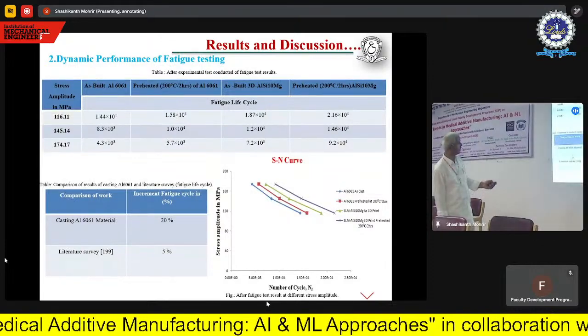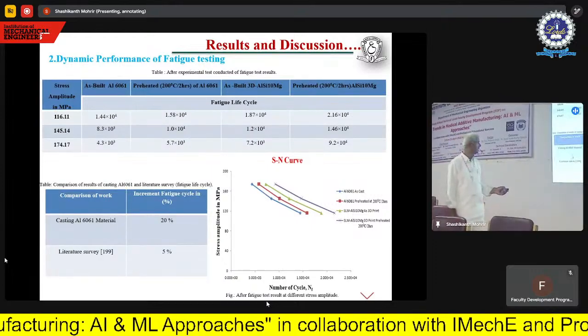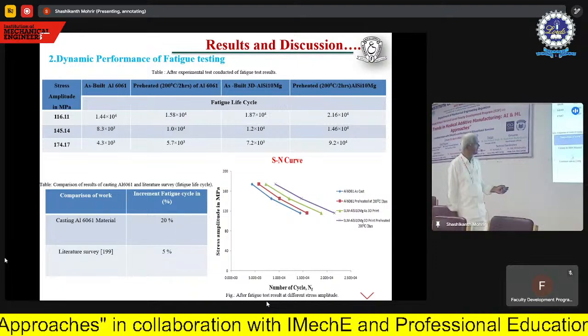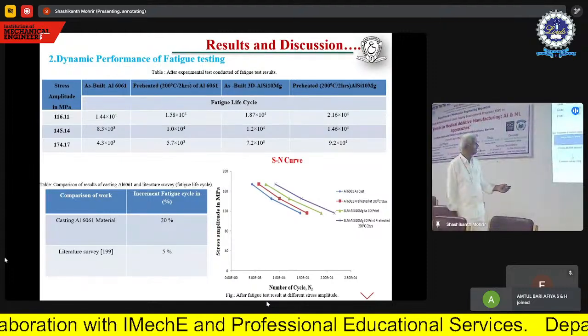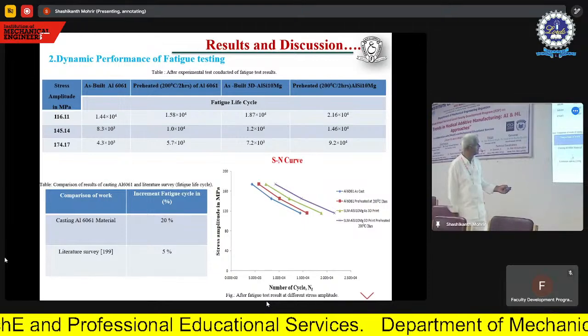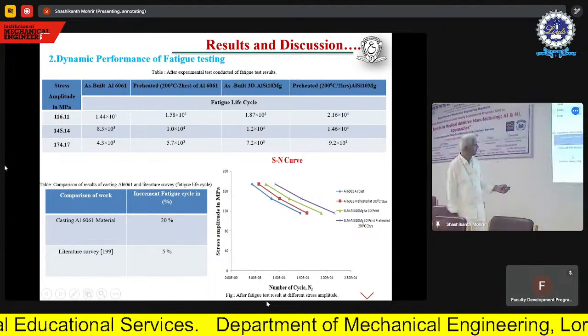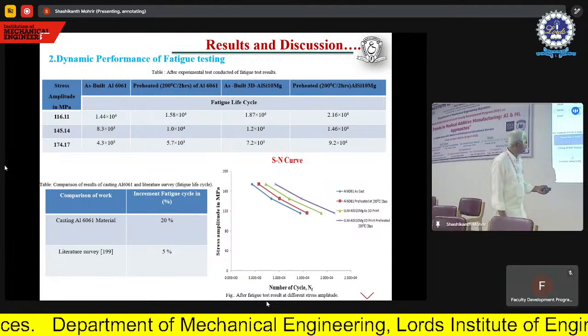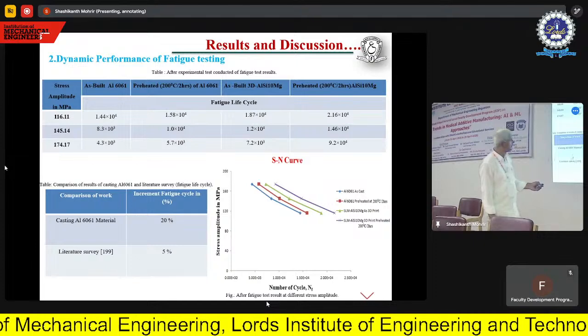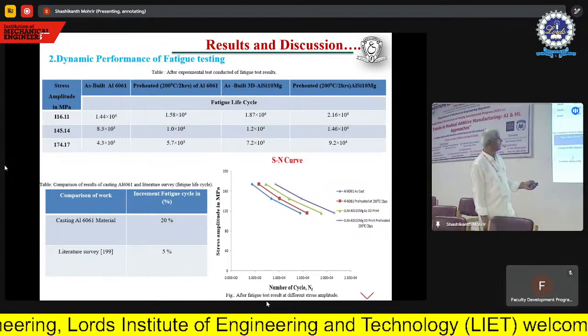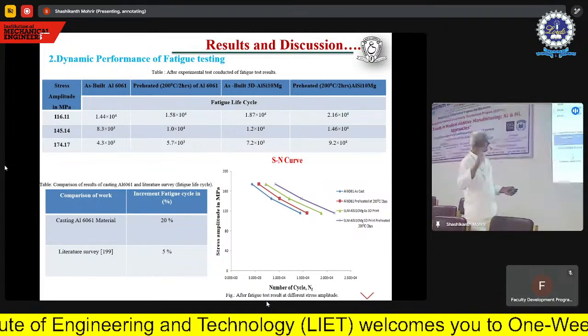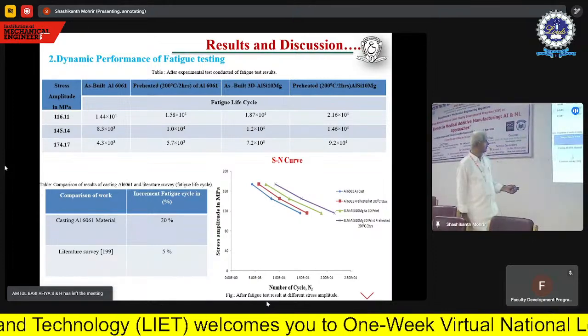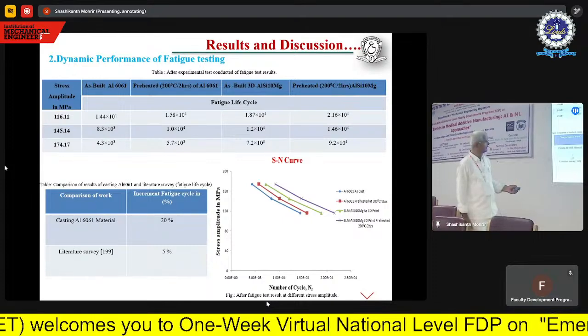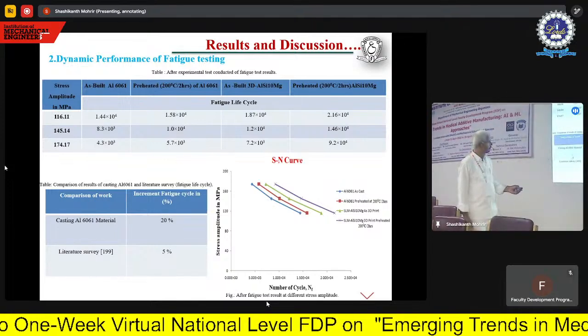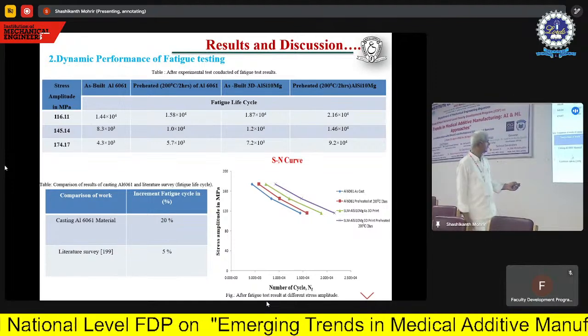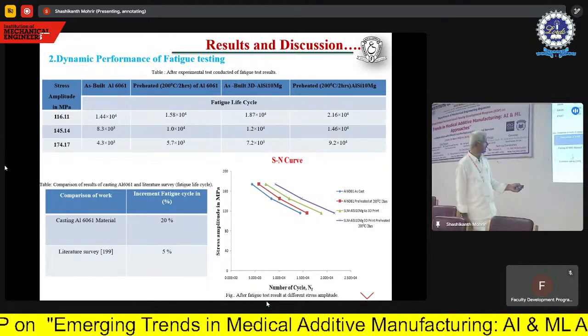Okay. So the SN curve. Approximately we try to build. So as cast, this is from a reference paper, preheated is our work, and as printed is getting better performance, and preheated to 200 degrees centigrade. Sorry, this red one is as cast, as manufactured, whereas this green one is as printed, and this violet one is our preheated. So number of cycles and also load increase.